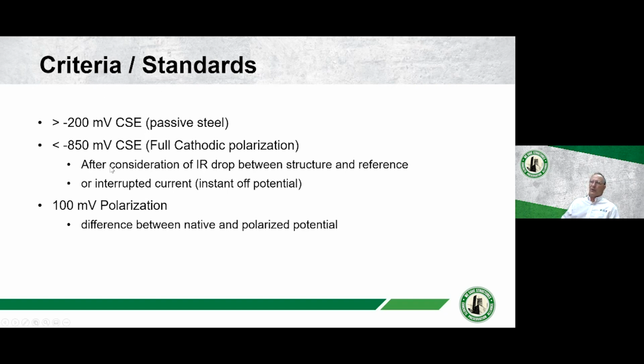And this is only after consideration of IR drop between the structure and the reference electrode, because there is current flowing through the electrolyte. The distance between your reference electrode and the structure has a resistance, and if the current is flowing, V equals IR means you have a voltage drop across that soil, and if it's 10 or 15 millivolts, you have to add that to the 850. Or you can interrupt the circuit and take your measurement. It's what's called an instant off potential. So if you have minus 850 with an instant off potential, you're good to go.